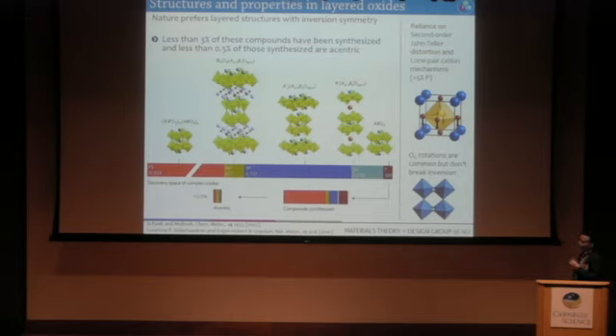Well, if you use a traditional mechanism for lifting inversion symmetry, something like the second-order Jahn-Teller effect, you're typically limited to early transition metal chemistries, or chemistries which have lone pair electrons. Okay? The other complication in this factor, and we heard a little bit about this yesterday, is that there are competing distortions in these types of structures which are centrosymmetric. Okay, and these will occur when you have very different ionic sizes for your cations, and these preserve inversion symmetry, and they can compete with those mechanisms which lead to polar displacements and ultimately broken inversion symmetry and perhaps a ferroelectric polarization.